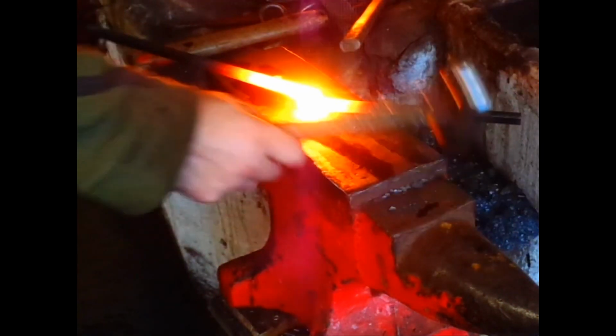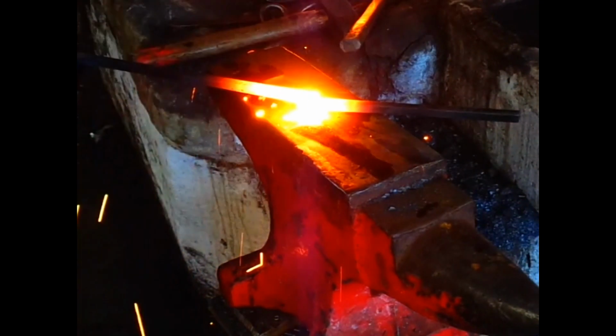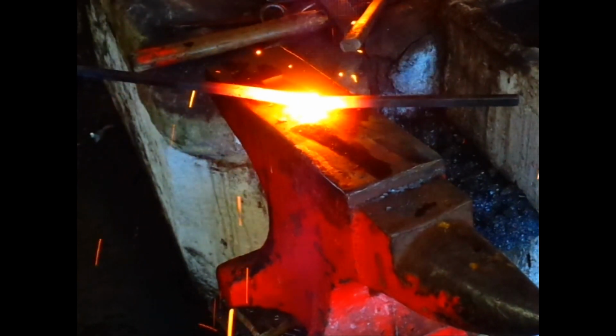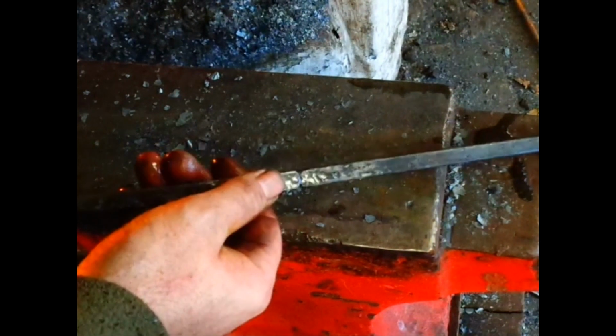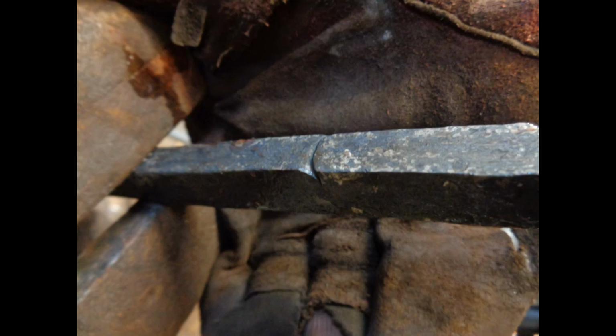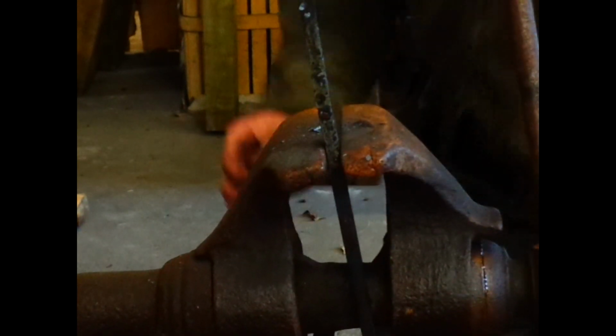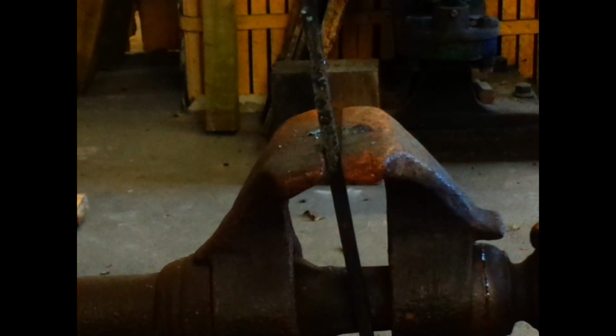These two pieces have been welded without a scarf. After a quick clean-up, the damage is clear and as predicted. The two straight ends have simply sheared through each other, causing a deep gore. A quick destructive test will show that it isn't purely a cosmetic problem, as the weld has no strength.